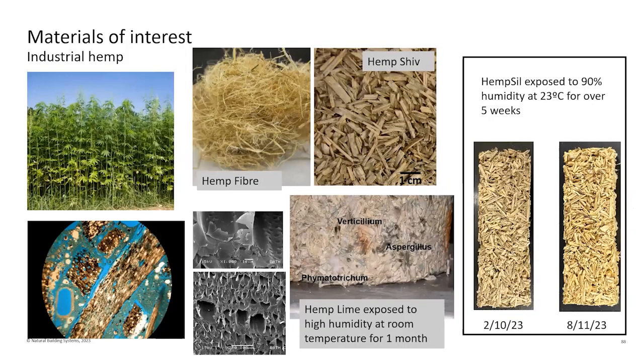We are particularly interested in hemp, and that's one of the things we're doing in this CHCX3 project. We're looking at manufacturing not just hemp-based materials, but also working with other materials. But on hemp, what is so interesting are the relative different sizes of pores. What this allows moisture to do is to move through the pores and condense and evaporate. In doing so, you're making use of the energy involved in changing phase. And this gives it an increased thermal mass, much more than its physical mass.